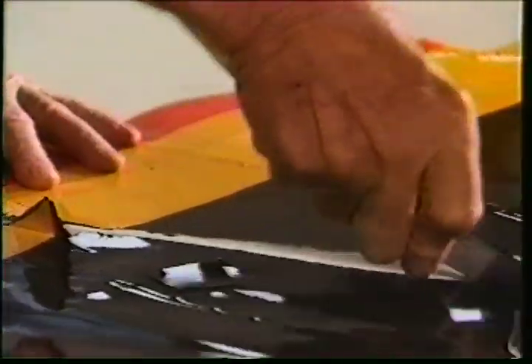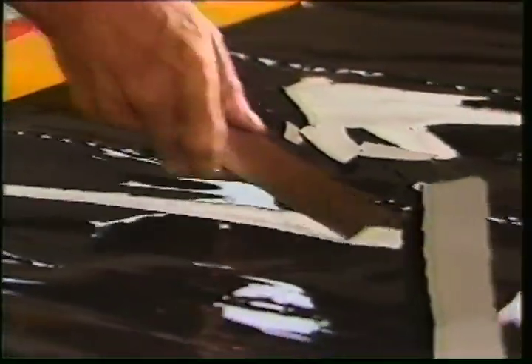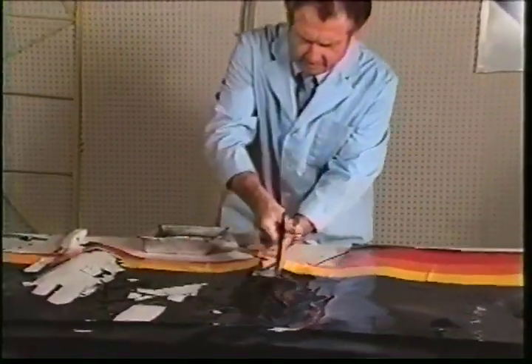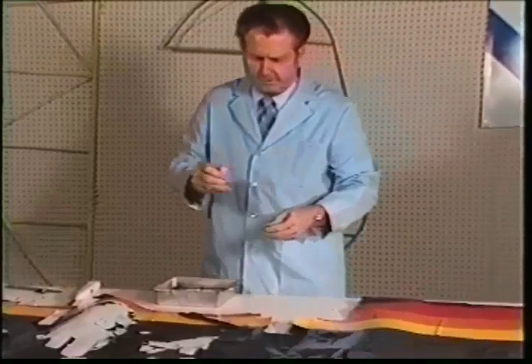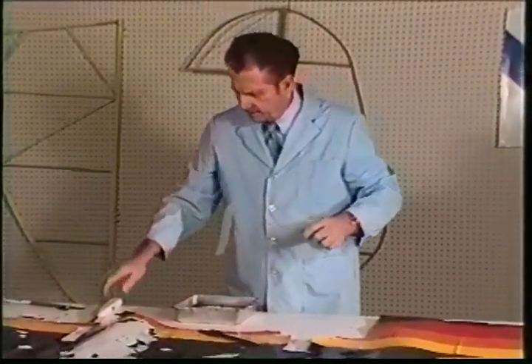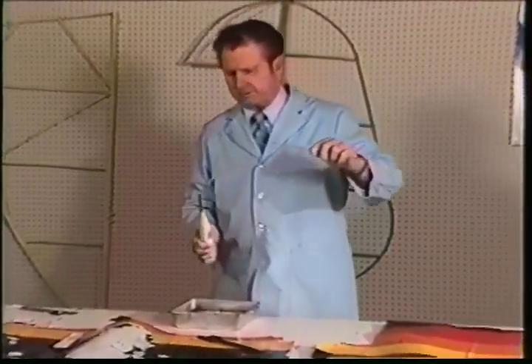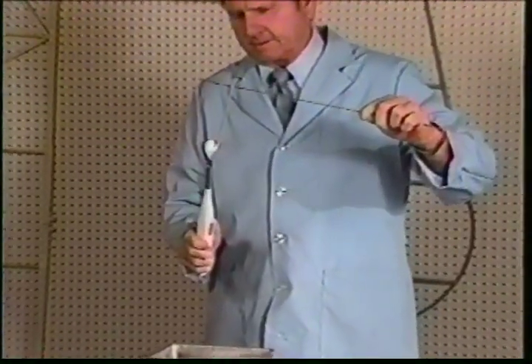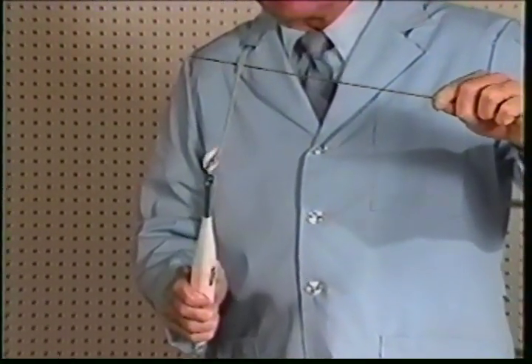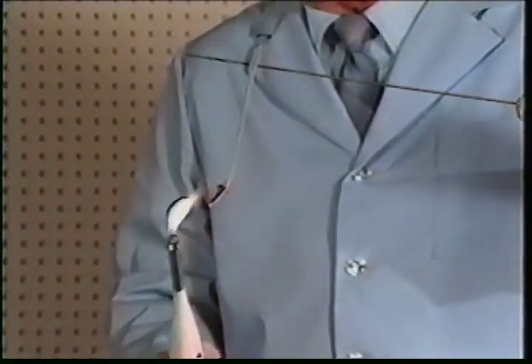fabric bare. We've seen the flammability of the other coatings and will now check the flammability of this acrylic-based polyurethane on polyester fabric, which is advertised as being non-burning. It ignites at a higher temperature than cellulose coatings. However, once started, it burns longer and just as hot.